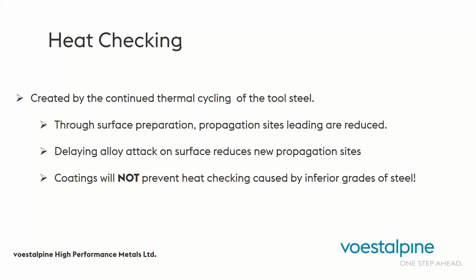We've seen many applications that have been very effective with that, and they can prevent heat checking, because those peaks and valleys are potentially propagation sites for heat checking. So you remove those propagation sites, you apply the coating on top, and you'll get good performance.